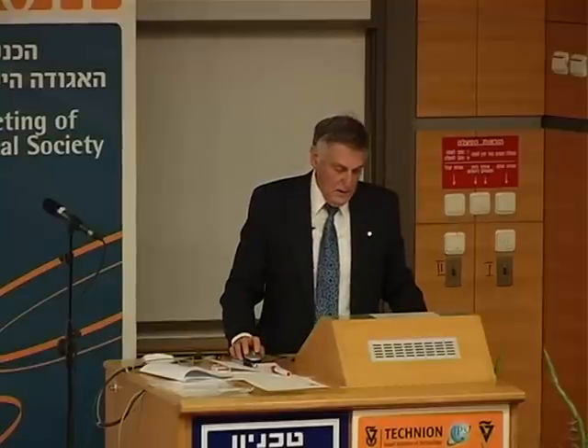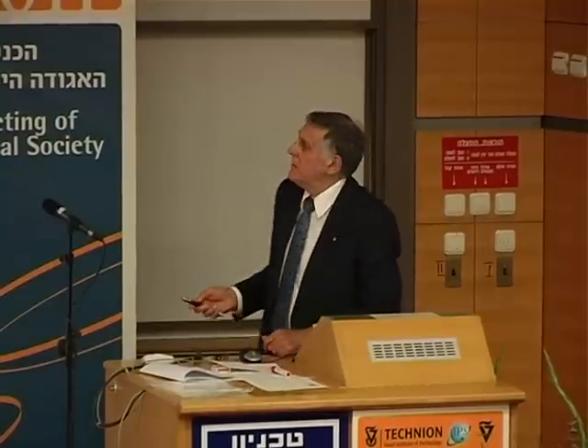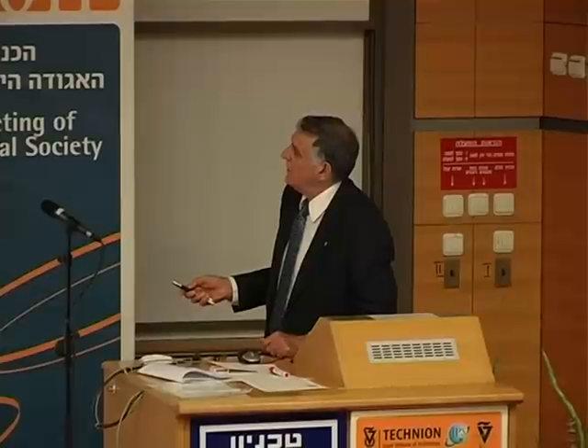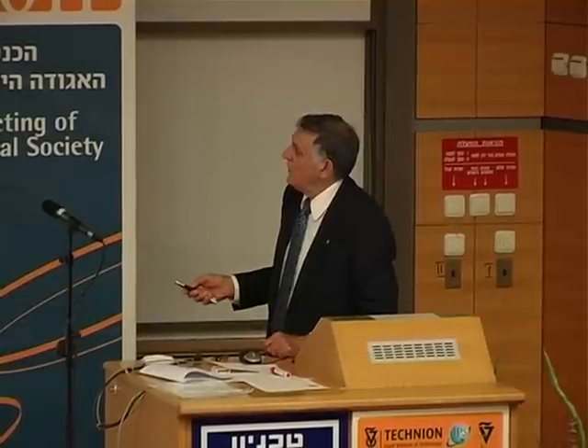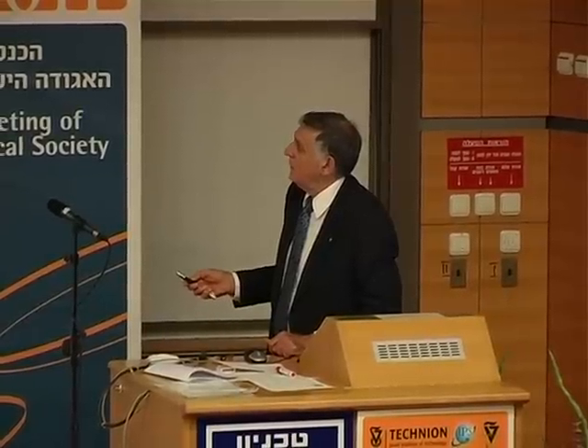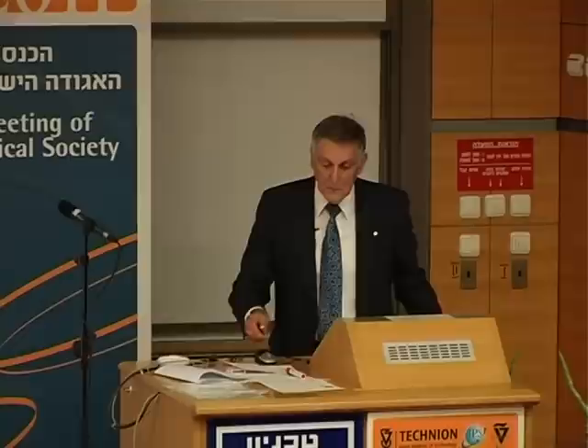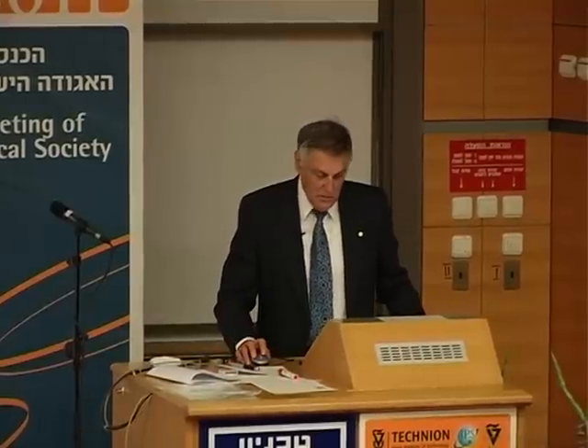And consequently, if you form the image with the transmitted beam, you see it's very dark because all the beams are diffracted and stopped by the objective aperture. Only one beam goes through. And then I said, wow, that's interesting. Let's look at the diffraction pattern. And I will show you soon the diffraction pattern. Select the diffraction, tenfold. That's odd. So let's go and see first the crystal.